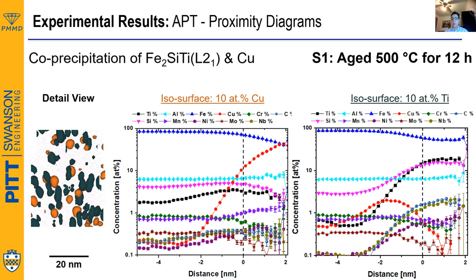If we look at the 12 hours aged sample S1, we see the same behavior. We see an increase of titanium and silicon in the vicinity of the interface between copper and ferrite, and then we see copper content increasing close to the interface between the ferrite and the L21 phase. Another important feature to highlight from this plot is that when looking into the interface between ferrite and L21, which means at the nucleus or closer to the nucleus of the L21 precipitate, we see an increase in niobium, which then confirms the finite solubility that L21 has of niobium